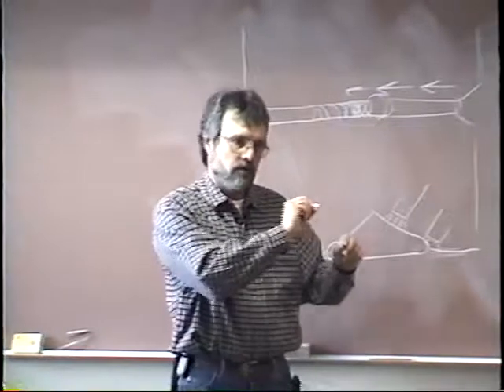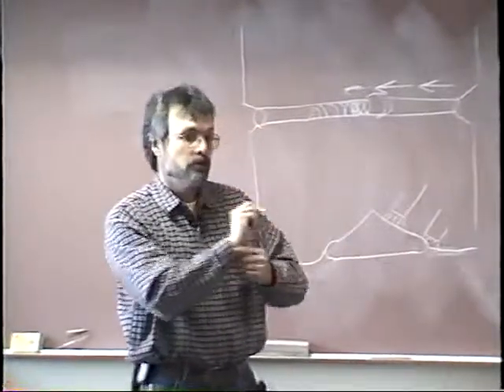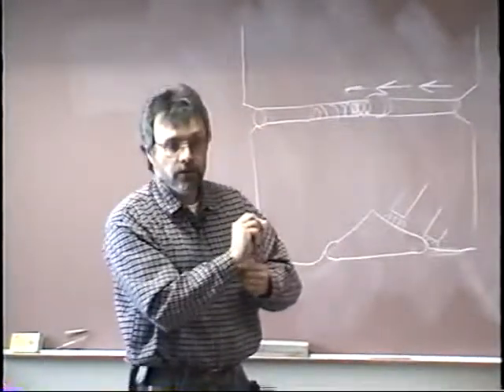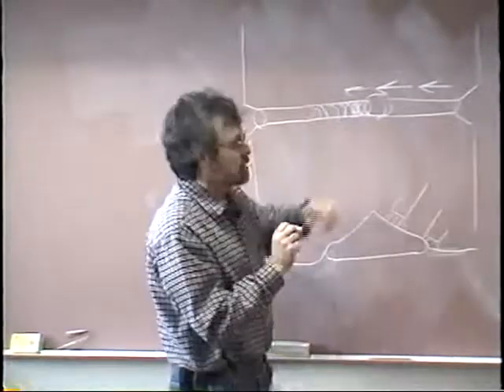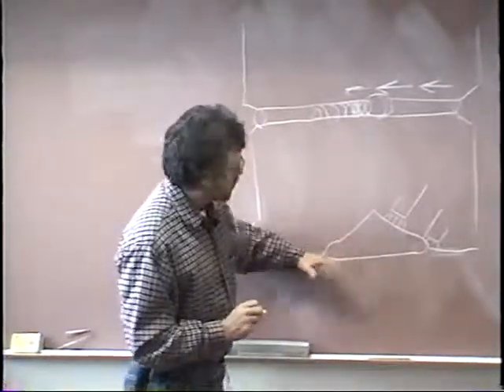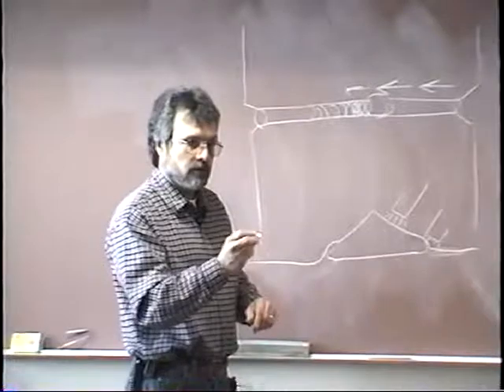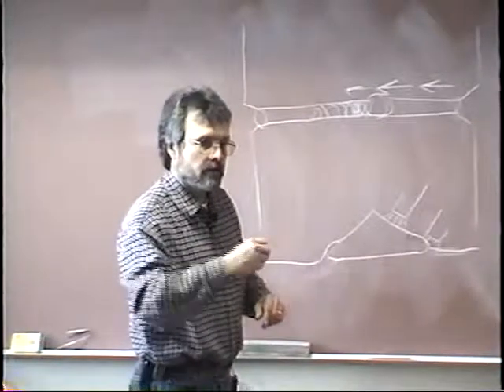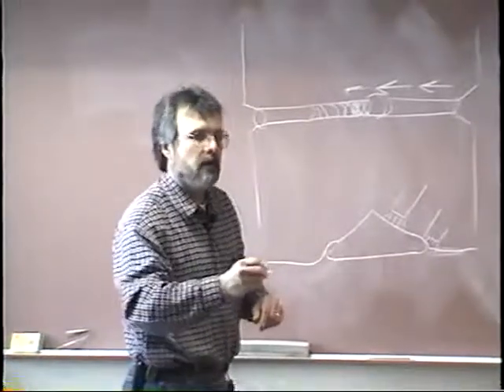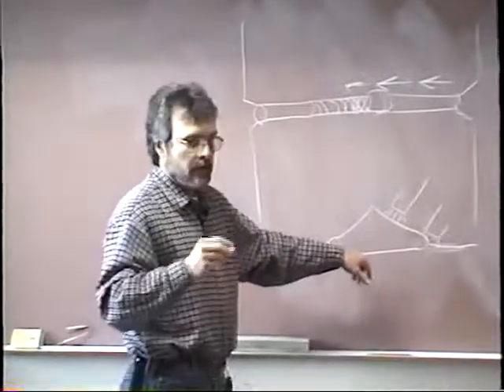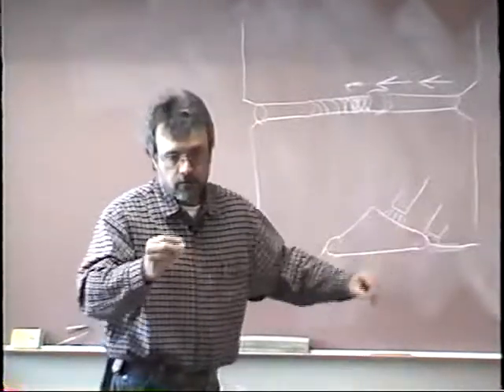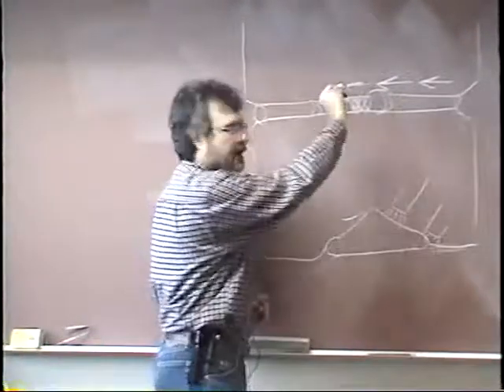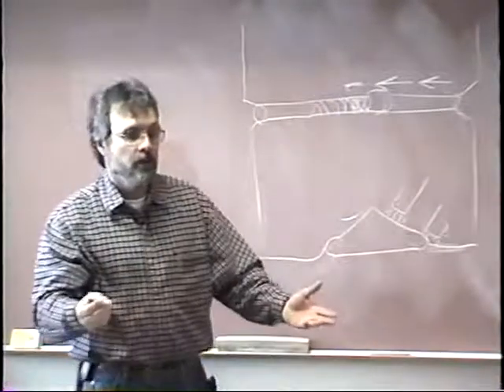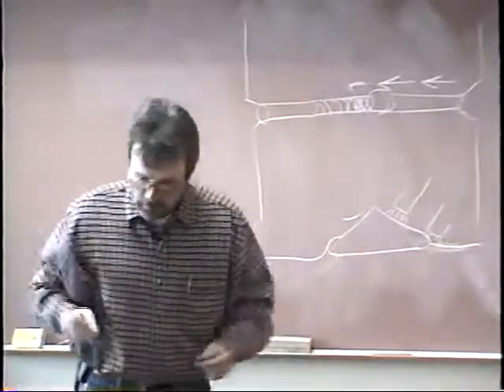Like I said before, I like to use a drag or a push when I'm putting in a root bead. But when I'm coming up to a tie-in, especially coming into one, use that whipping motion, you just kind of step forward and back, step forward and back, step forward and back to preheat that tack. And then once that ties in, then you can go ahead and just flick it out. And that's what he means by quenching. You get away from it quickly.